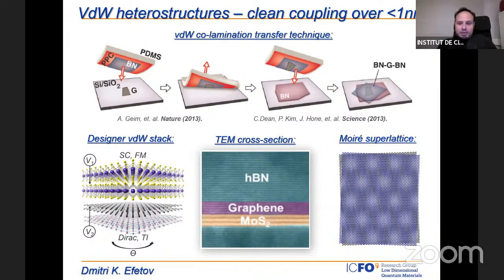While initially, when this work was done, I think very few people would have bet that this would work so well, TEM cross-section measurements of such stacks revealed that the interfaces between these materials are extremely good. Here you can see that between hBN, graphene, and MoS2, you really find atomically sharp interfaces. And last but not least, of course, the moiré superlattice. This is a relatively novel concept in heterostructures, that all these layers, we can assemble them at an arbitrary twist angle between each other.